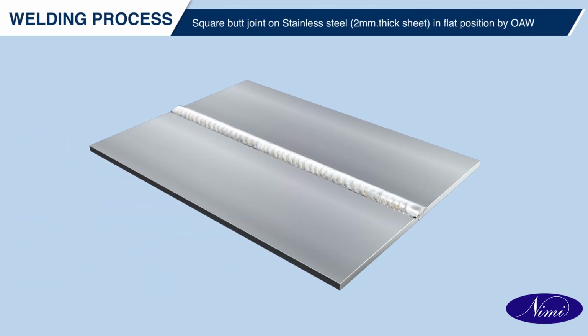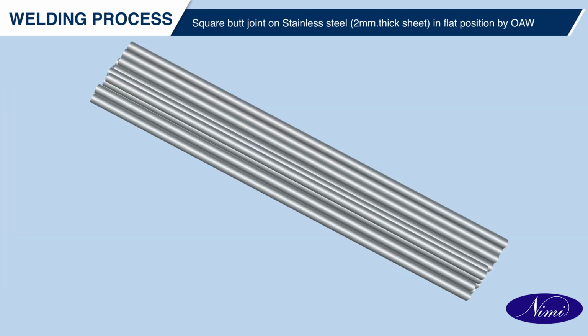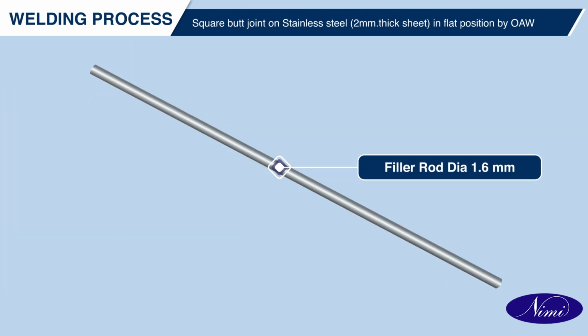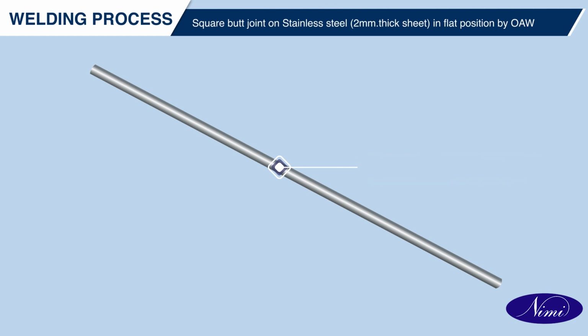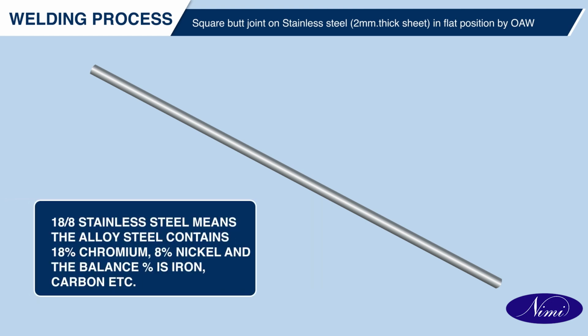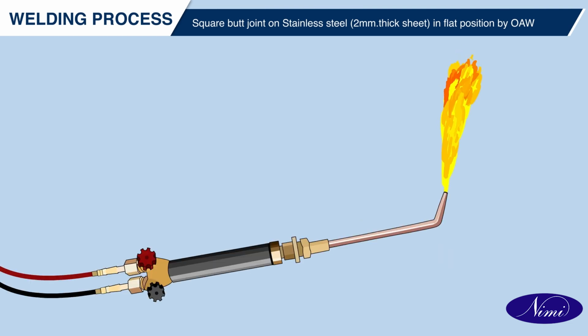Now let us learn about the welding process of square butt joints on 2 mm thick stainless steel sheet in flat position by OAW process. Select a 1.6 mm specially treated chromium bearing 18 by 8 type stainless steel filler rod or cut strips from the base metal to use as filler rod. 18 by 8 stainless steel means the alloy steel contains 18% chromium, 8% nickel, and the balance percentage is iron, carbon, etc. Set a strict neutral flame or slightly carburizing flame so as to prevent the formation of oxidizing flame which is harmful.